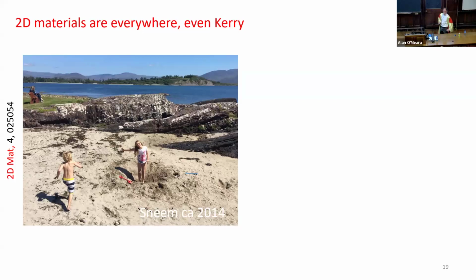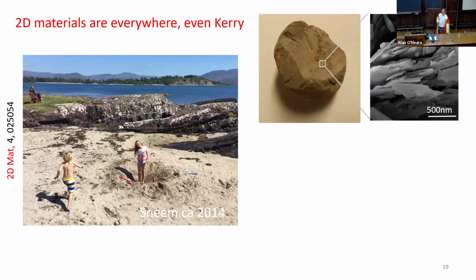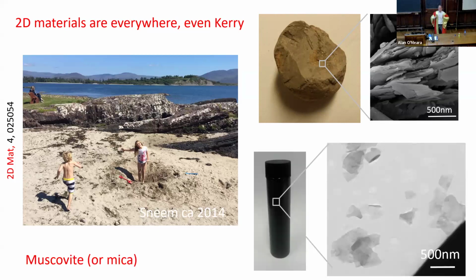So being the nerd that I am, I collected some of the clay, brought it back to the lab. That's an electron microscope image of the clay. And can you see the sort of layered strata? And that shows that there are layered materials in the clay. We then ran the clay through our process, and you see we found lots and lots of 2D materials, and these are mica. Not very exciting, but 2D materials made from clay found on the beach in Kerry. So I think that's pretty cool.